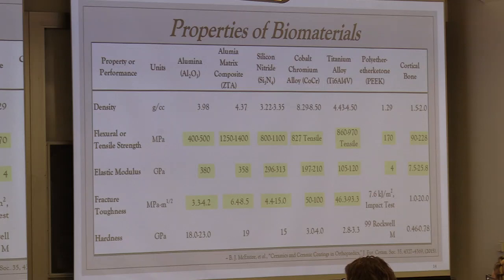The other important thing to look at is the elastic modulus of the material. Ceramics have very high elastic modulus. The metals also have a high modulus as well. So the reason PEEK is in here is that it is a material which has a modulus which is in the range of bone. And why is that important? Because if you're trying to interface with bone, you want to prevent what's called stress shielding. That is, the device that you're putting in conforms to the tissue or the bone surface that you're applying it to. So that's why PEEK has become a very popular and important implant in the industry.